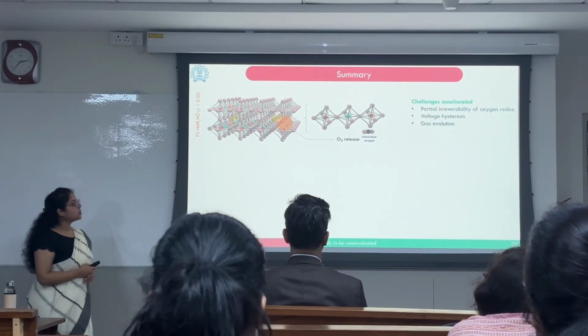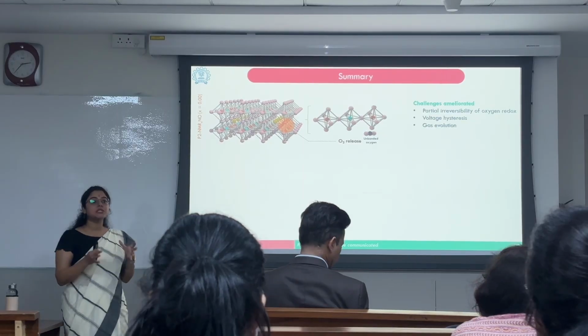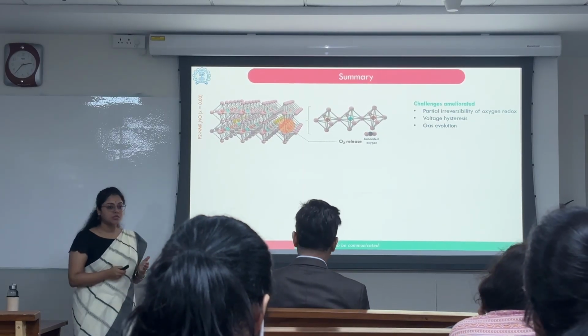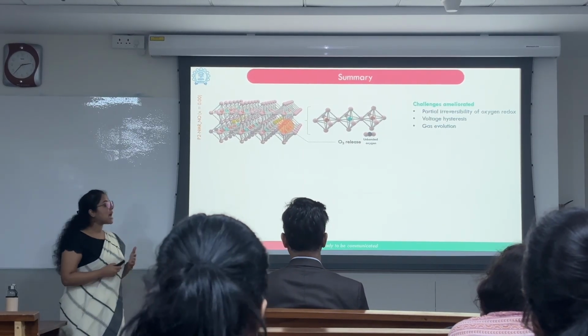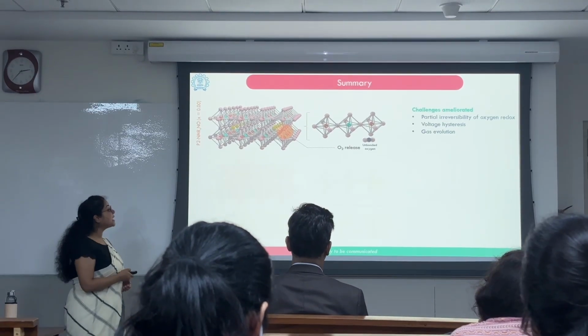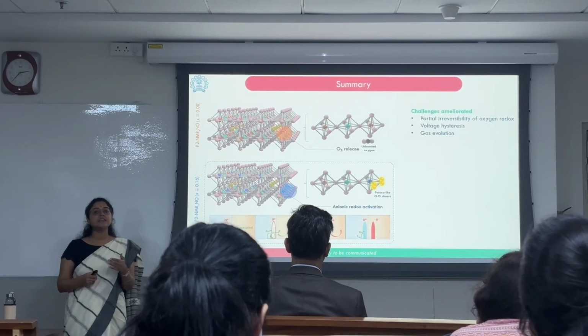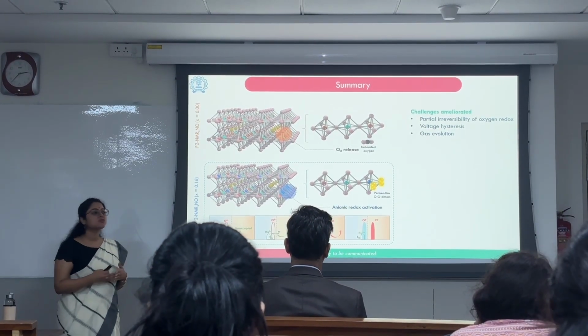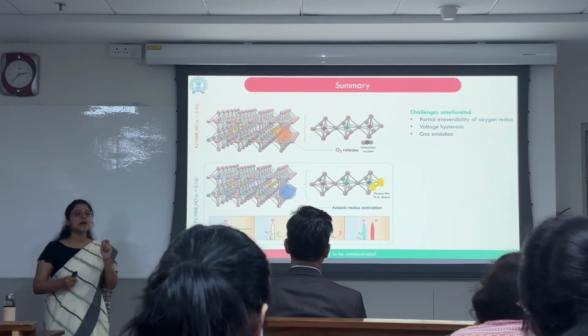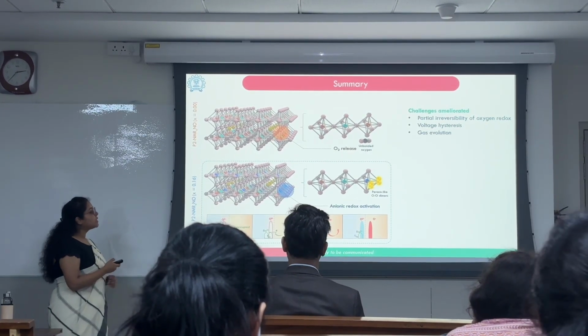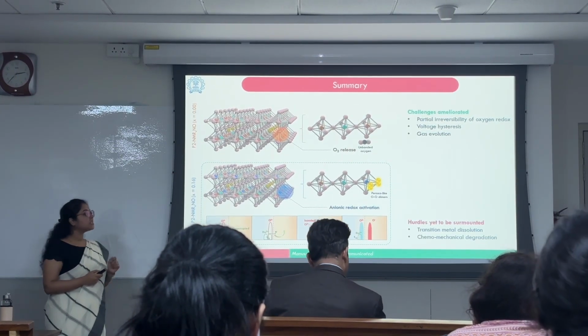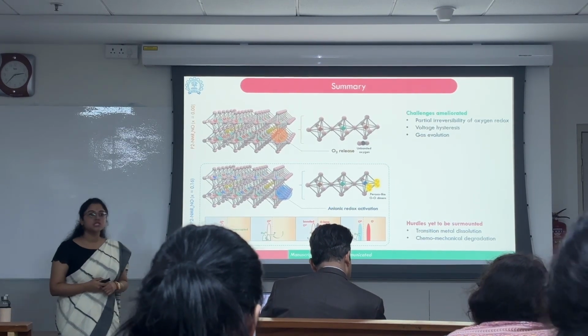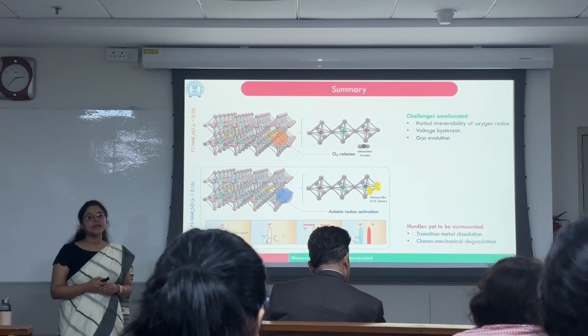So in this particular chapter, we dealt with the partial irreversibility of oxygen redox, voltage hysteresis, as well as gas evolution by doping ruthenium and activating the ligand to metal charge transfer mechanism in order to make it partially reversible. There are certain challenges that are yet to be addressed, which are the transition metal dissolution and chemomechanical degradation.